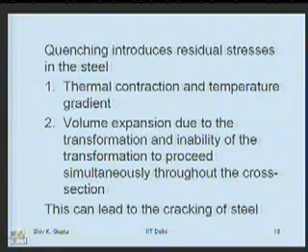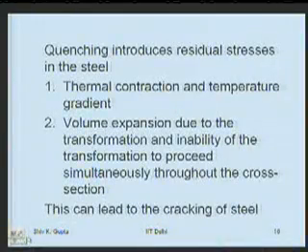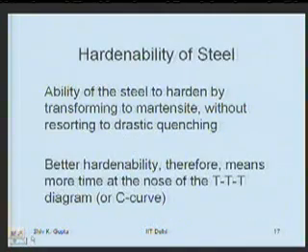And I told you, if you take any plain carbon steel and quench it from the austenite temperature, invariably it will crack if you quench it in water. However, we may stop this cracking if we do it in a slower process like dropping it in oil. Maybe you can stop cracking. Now, how to overcome this problem is very essential for us. It's a very serious problem.